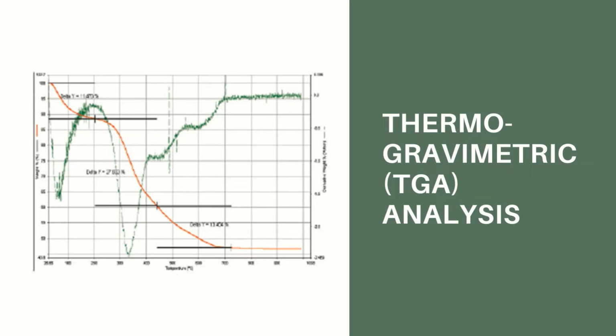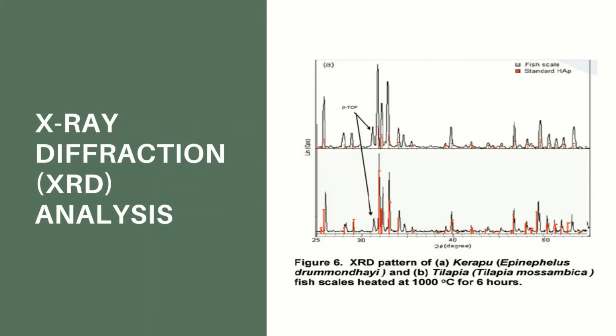Based on the graph obtained from the TGA analysis, it is confirmed that there is the presence of both collagen and hydroxyapatite. When the fish scale is heated up, the organic material, which is the collagen, is burned off and used up, in accordance with the red line on the graph. The inorganic material, which is hydroxyapatite, will remain. Therefore, we are able to calculate the percentage of both materials.